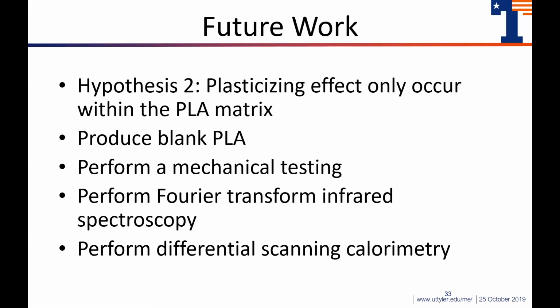And then lastly, we'll perform differential scanning calorimetry. This will allow us to see if the glass transition temperature and the melting temperature have changed in comparison to the original. This also will let us see if there's a change in the intermolecular bonds, because when those bonds break, it'll probably decrease the glass transition and melting temperature.